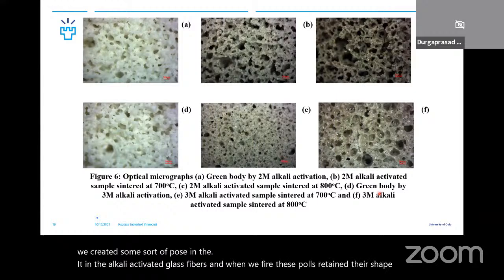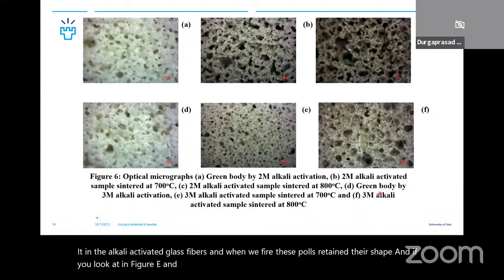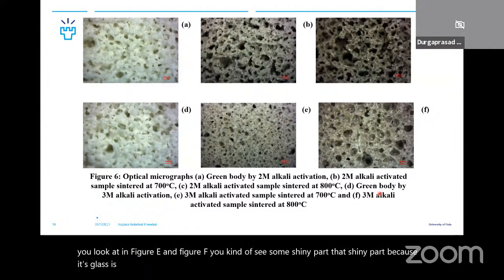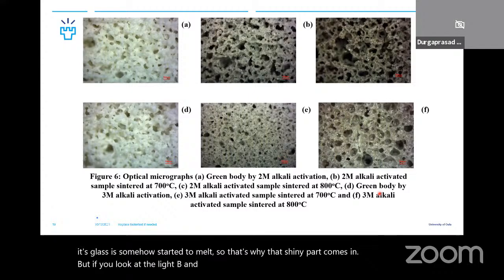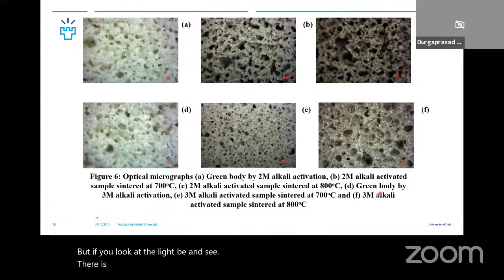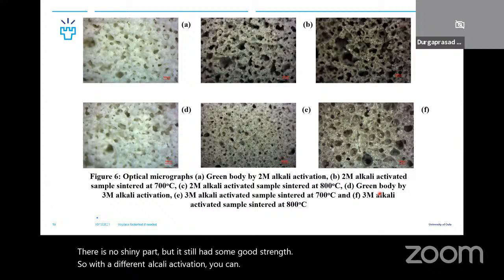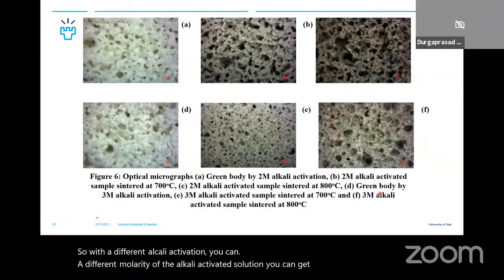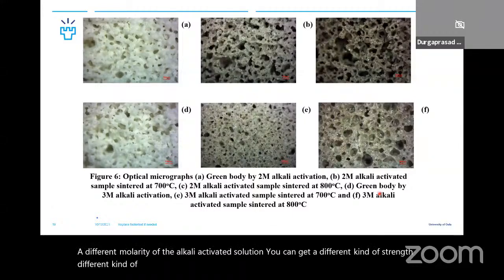If you look at figure E and figure F, you see some shiny part. That shiny part comes in because the glass has started to melt. But if you look at B and C, there is no shiny part, but it still had some good strength. So with a different alkali activation, a different molarity of the alkali activated solution, you can get a different kind of strength and different kinds of pores, and you can tune the material according to your need. So that is one thing.